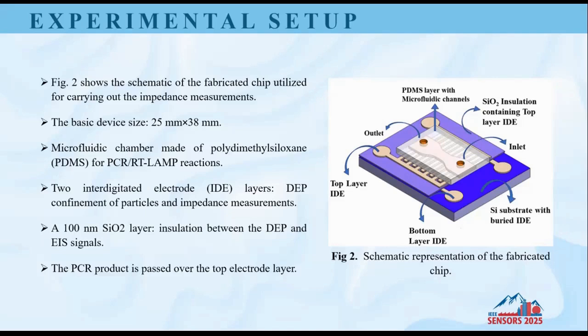So here, the schematic of the fabricated chip utilized for carrying out the impedance measurements is being shown. The basic device size is 25 by 38 millimeter square in dimensions and consists of a microfluidic chamber made up of polydimethylsiloxane for PCR or RT-LAMP reactions and 2 interdigitated electrode layers for carrying out DEP confinement of particles. So DEP means dielectrophoretic confinement of particles, as discussed earlier, and impedance measurement. So these are the purposes of using twin electrodes in our case.